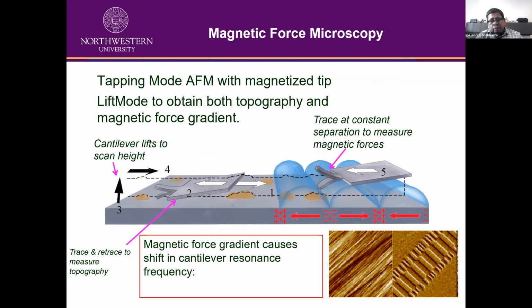So basically you can take a topography image. And then it lifts, turns the feedback off, and moves the probe at a constant height. And then if there's a magnetic gradient there, because we have to use a magnetic probe here, that magnetic gradient deflects the cantilever. So basically it shifts its resonant frequency. The shift in the frequency of the cantilever is basically equal to the magnitude of the magnetic force.